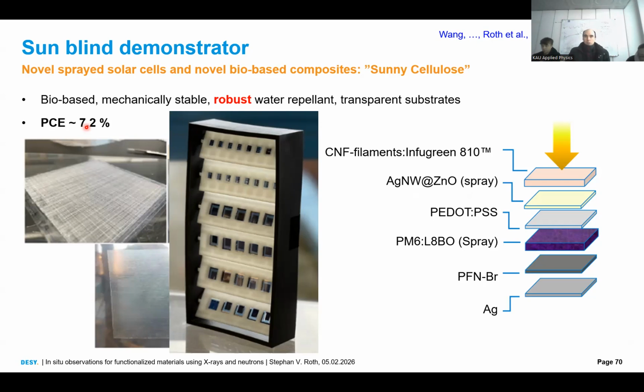And what is the minimal thickness of such a layer that you can still have while functional? It depends a little bit on the material used and on the solvent. It can be as low as 20 nanometers or as high as 100 nanometers. In that range, you can have functional substrates.